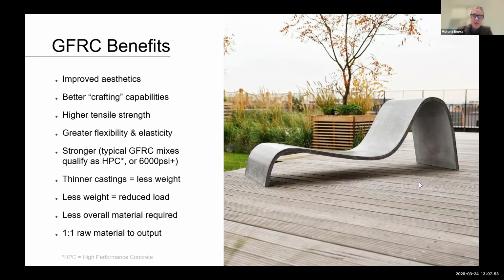Compressive strength also improves by virtue of the Portland cement increase, and it typically pushes this GFRC into the realm of high performance concrete, which is 6,000 PSI or more. So what that means is that GFRC pieces can be cast thinner than traditional concrete while exhibiting equivalent or greater strength. And the thinner pieces are also lighter. So GFRC improves efficiency really by achieving more than traditional concrete, but with less material.